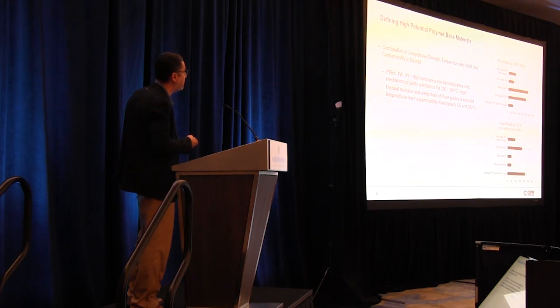So I'm looking at flex modulus as a measurement of the mechanical properties at 200 degrees C. And you can see the PEEK and polyimide excel, or are actually greatly improved over the PTFE grade here. And also, let's look at the creep results. So this is a measure of the flow properties. So it's the amount of flow with a constant load at 200 degrees C. And again, with polyimide and PEEK, and even with the polyamide imide, you get great improvements compared to the PTFE. So lower levels of flow associated with the deformation. So again, these are really good candidates to consider.